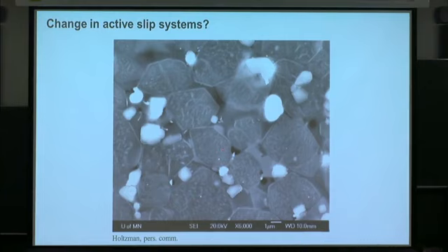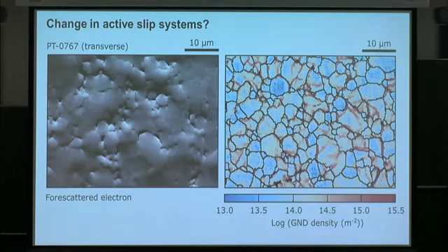Okay, so tons of dislocations in there. We've been working with the Department of Materials at Oxford, and there are some guys there who are really good with electron backscatter diffraction. They've developed a technique that gives you magnificent angular resolution, on the order of a few thousandths of a degree. Once you have data that precise, you can undergo a calculation that I won't talk about unless necessary, that lets you calculate the dislocations that must be there in your sample in order to generate any curvature.